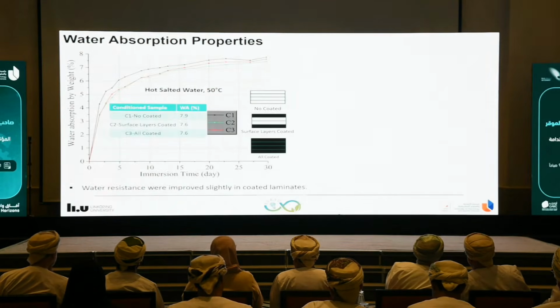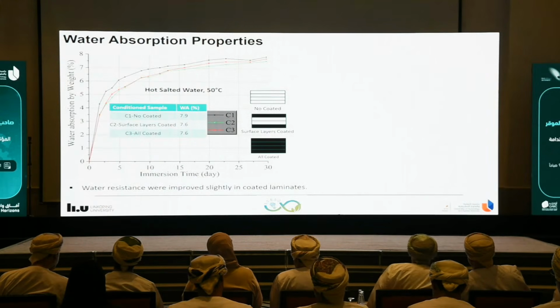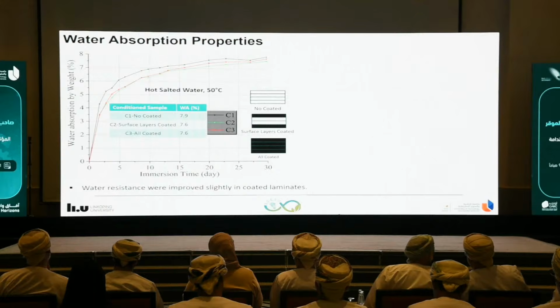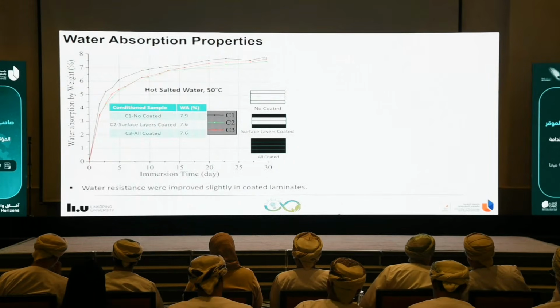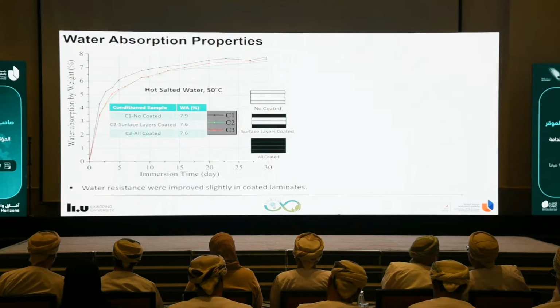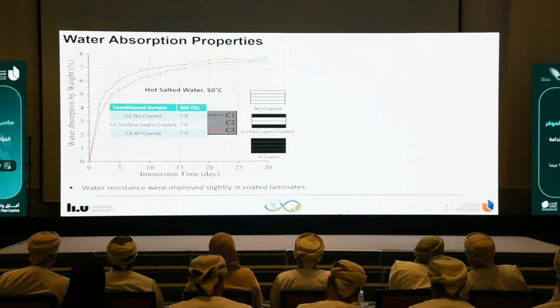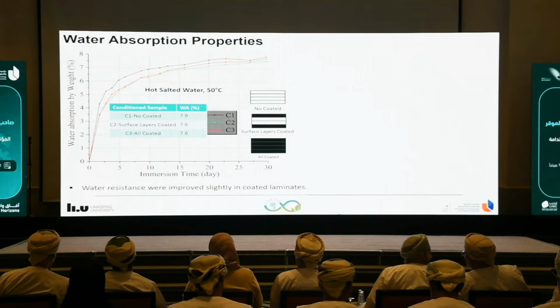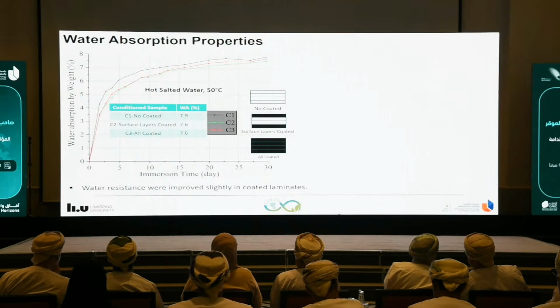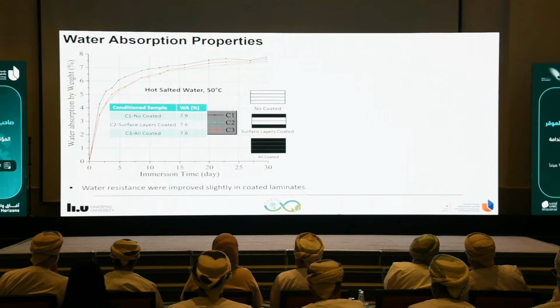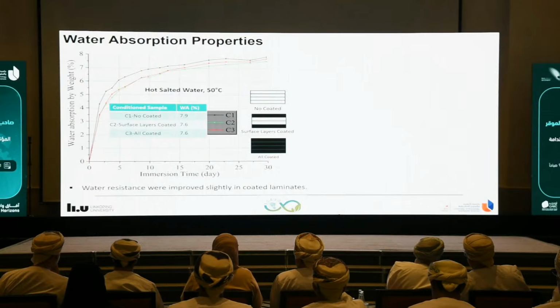So after that, we did testing. The first test that we did was water absorption for 1 month. We put all the parts that we manufactured in water, hot water and salted water, for 1 month, and every day we were weighing the structure to see how much water it absorbed. And as you can see here, you have in percentage how much water they have absorbed, and we didn't see a big difference.